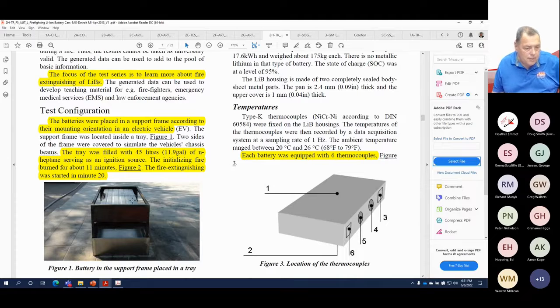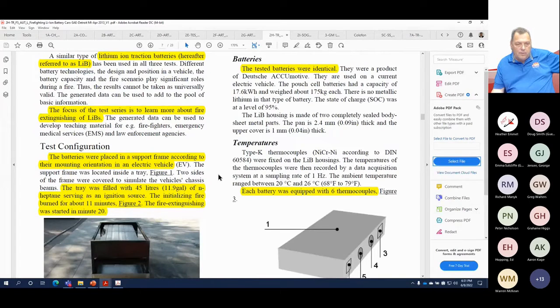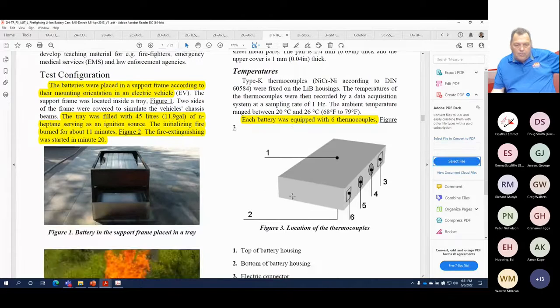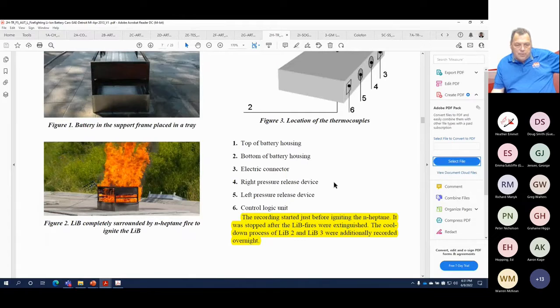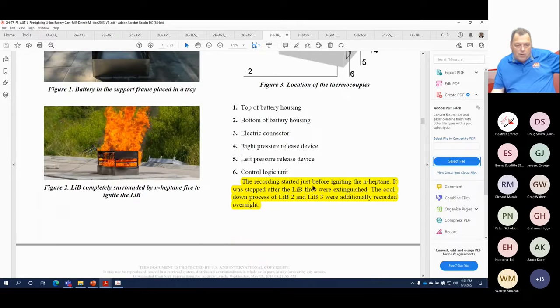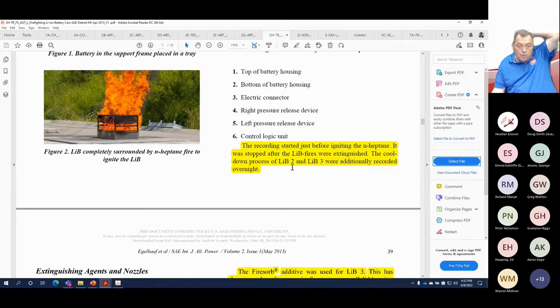These were the test configurations where they put the batteries over top of heptane. The tray was filled with 45 liters of heptane, serving as an ignition source and burned for about 11 minutes. The fire extinguishing was started in 20 minutes. In all tests, the batteries were identical. Each battery was equipped with 6 thermocouples. So this is showing the batteries. Recording started at the beginning of the heptane and was stopped after the batteries were extinguished and the cooling process was done.